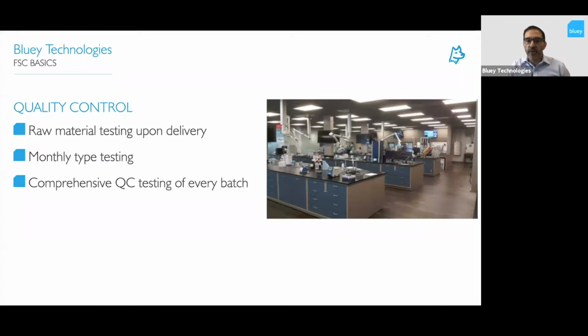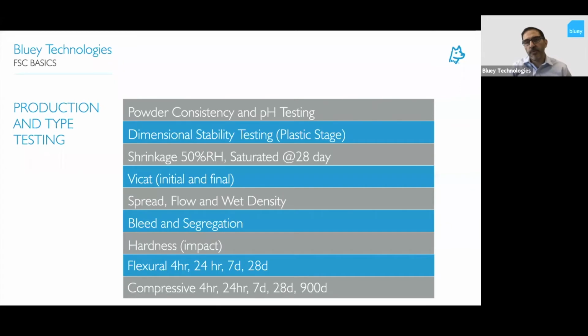So we've got that data, which is being done monthly, and we're also testing every single batch that comes out. And when we say every single batch, each batch would be around half a ton of powder. So that's a lot of testing. And the type of testing we're doing, just to summarize some of those tests here, we've got powder consistency, dimensional stability testing during the plastic stage, shrinkage testing, bleed and segregation, hardness, and then obviously the mechanical properties of flexural strength and compressive strength. Doing that testing early gives us the opportunity to get that long-term testing before the product goes out to site and is put into application.